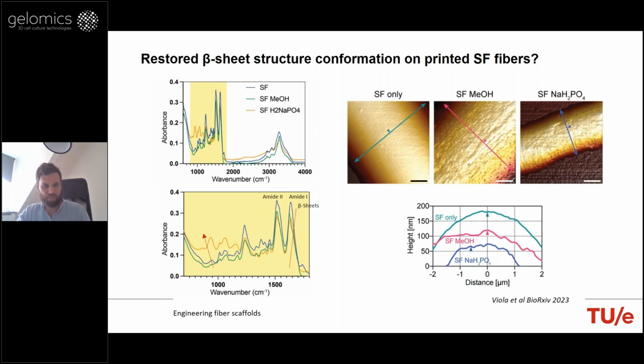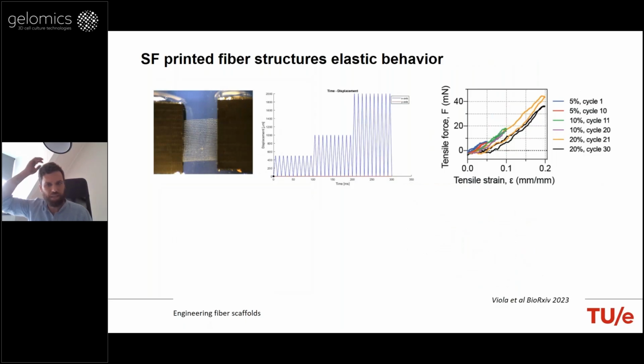Of course, this still requires in-depth analysis. We are now looking at the cross-sections of the printed filaments to confirm if there is indeed any crystallite alignment, and we are also looking at other techniques like SAXS to further investigate at the molecular level what is actually happening. What we could look at, without this in-depth understanding, at the micro scale is that the printed constructs treated with sodium phosphate showed an elastic behavior.